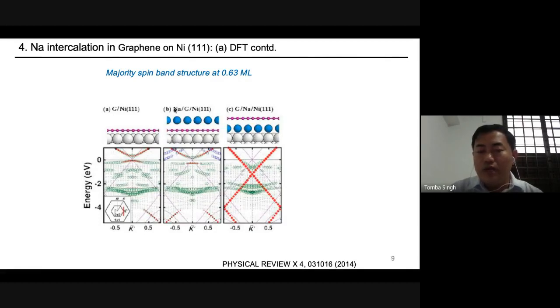If we adsorb the sodium above the graphene, the only addition is the surface state of the sodium, shown here by the pink or blue balls. But a drastic change we see in the case of the intercalation: here we see the proper Dirac cone, a proper Dirac band, in the case of the intercalation.